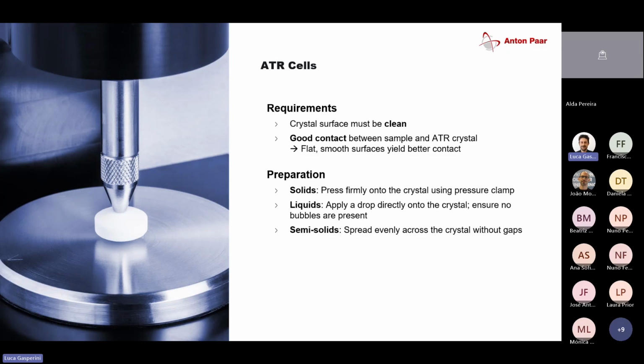Then for solids, there is not much sample preparation. There are some exceptions, obviously, like everywhere: if you have very, very hard samples, you may have to make powder out of them to get a better signal. But in general, for polymers, you're very good with just the solids without any sample preparation.